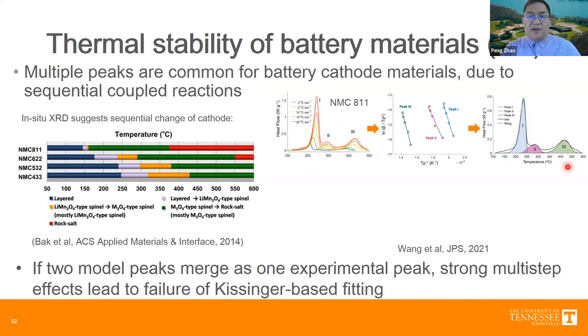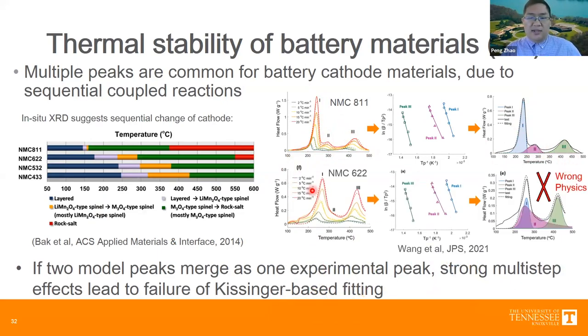However, if you take a look at another case, NMC622, now in this case, the first peak and second peak sort of overlap, they are merged. You almost cannot see the second peak. If you're still using three separate reactions to fit this DSC result of the material following the Kissinger method, now you can come up with some misleading results.